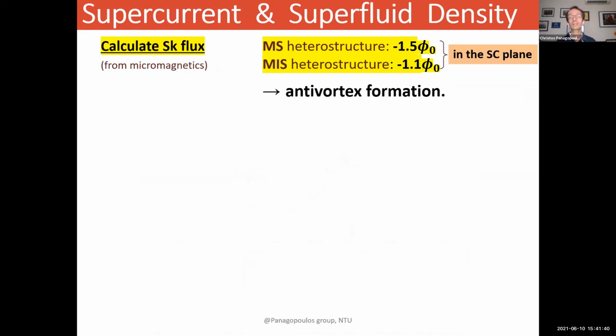So having this confidence, we can now calculate the skyrmion flux. And it turns out for the MS heterostructure to be minus 1.5 phi naught. Whereas for the MIS heterostructure, where the superconductor is separated from the magnet by an insulator, it is minus 1.1 phi naught in the superconducting plane. And this indicates the presence of anti-vortex formation, just as we expected from the quantitative calculations.